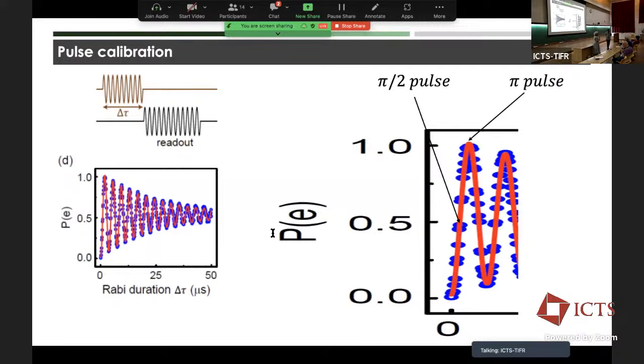So in the transmon, dephasing still happens, which basically tells you that it's not only charge noise which can cause dephasing. These are due to slowly fluctuating two-level systems in various parts of the circuit. It could be in the insulating barrier of the Josephson junction. It could be in the thin layer of oxide which covers all your metal surfaces. So imagine that you have a parallel plate capacitor, right? And there is some dielectric medium, but inside that medium there is some atom which is shifting between two positions over some small time scale.